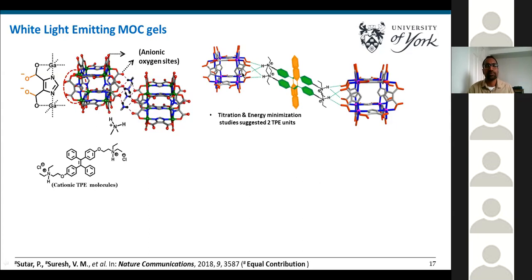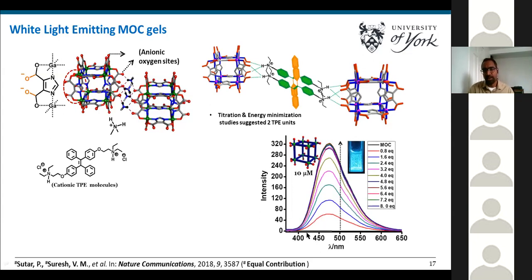Before going to the gelation, we tested whether they can interact through fluorescence titration. The black line here is the pure MOC solution, which is non-fluorescent. Now we started adding equivalents of this cationic binder. As we add TPE cation molecules to the MOC solution, the MOC started aggregating, which is evident from the fluorescence spectrum. With increasing addition of TPE, the emission intensity related to the TPE continuously increases, and it gets saturated at 6.4 equivalents.